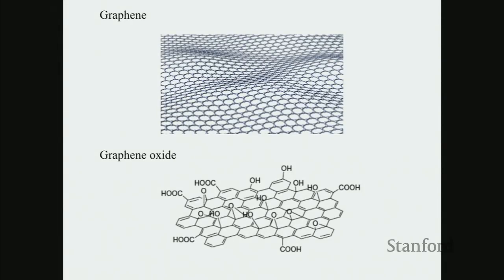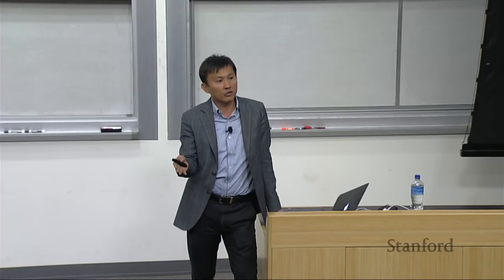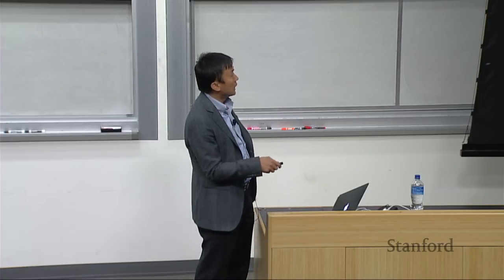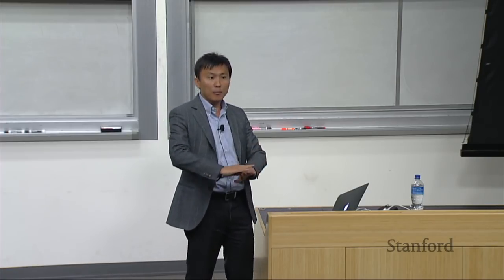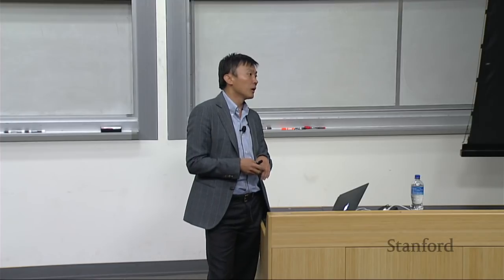These protons will be given away. So the reaction free energy, delta G, between lithium and graphene oxide, this surface reaction gives you a negative delta G, driving the reaction to happen. And that really means this lithium metal really likes the surface of graphene oxide, causing the wetting phenomenon to take place.